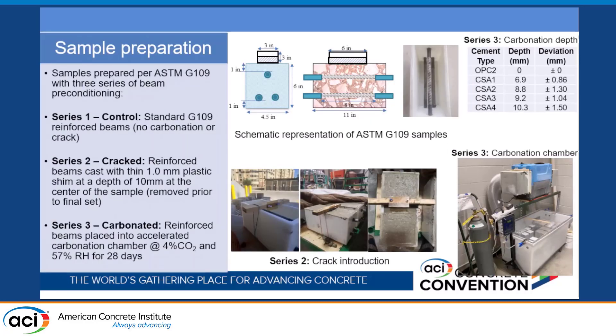For sample preparation, the samples for this study were done according to ASTM standard G109 with some modifications. We wanted to look at three different series: one is the control, which follows exactly what the standard specifies. We also wanted to look at two different series — one introducing a crack into the beam, and another looking at the effects of carbonation when these samples are exposed to carbonation, and how that affects the reinforced steel.